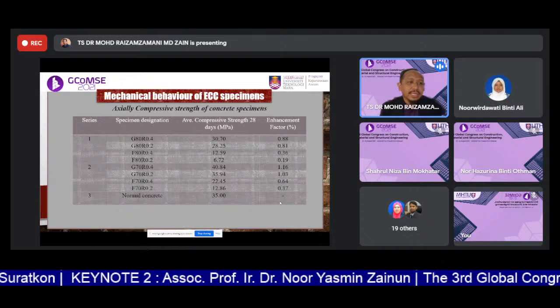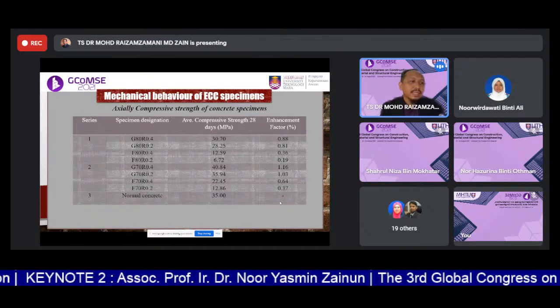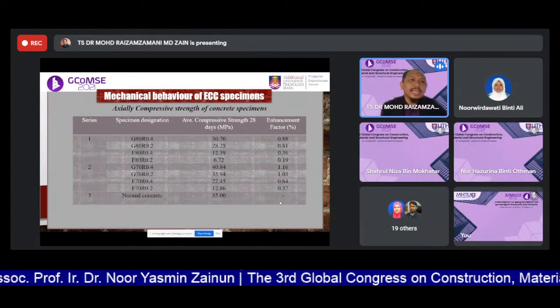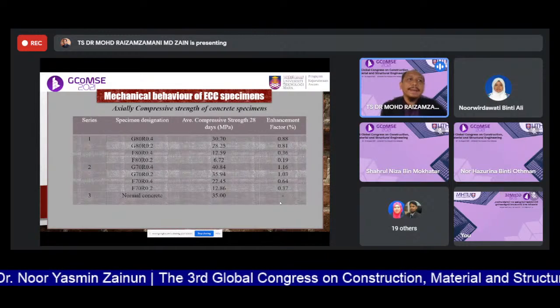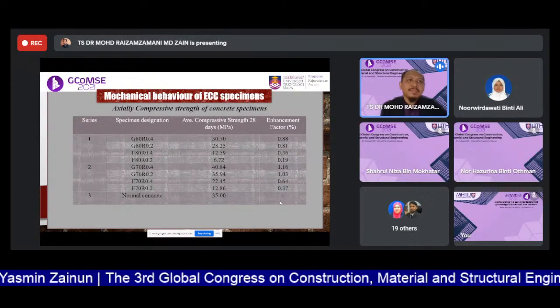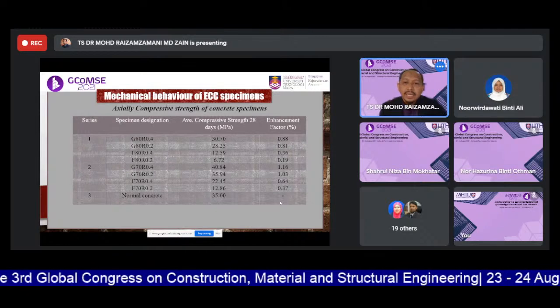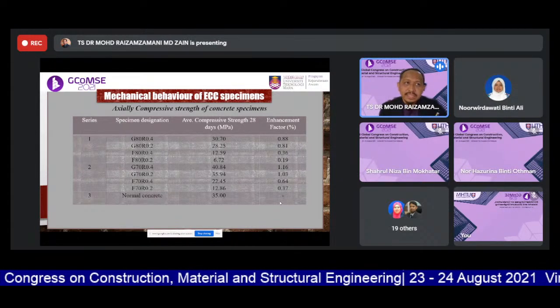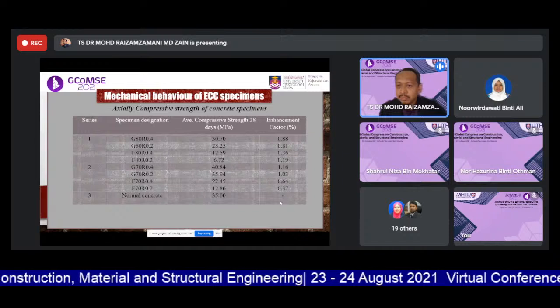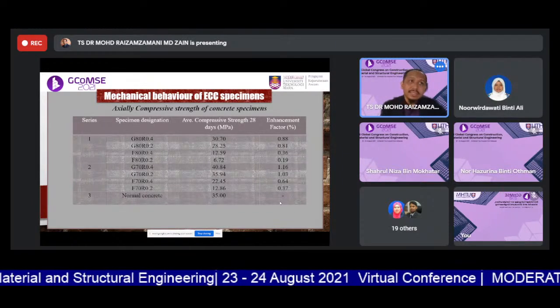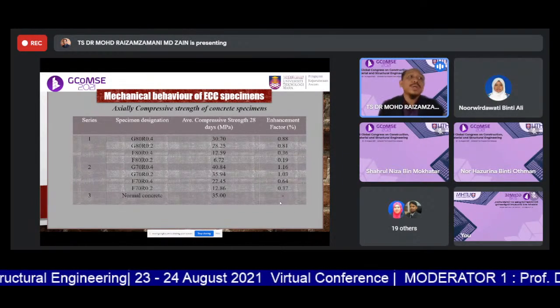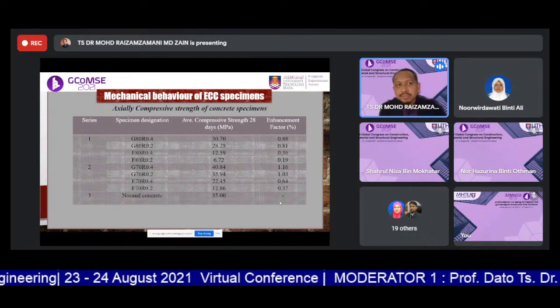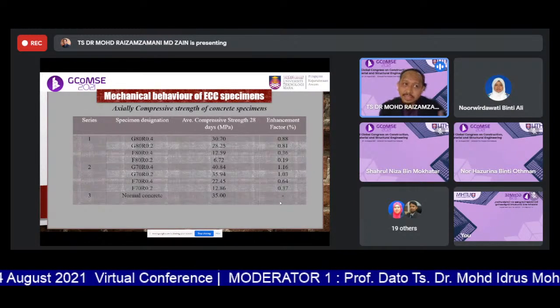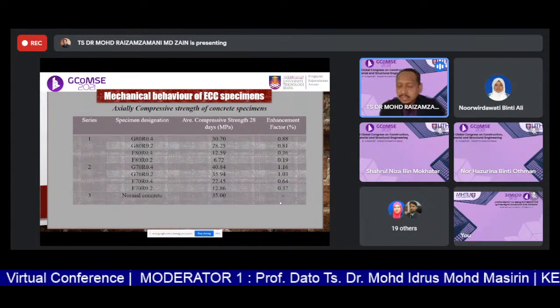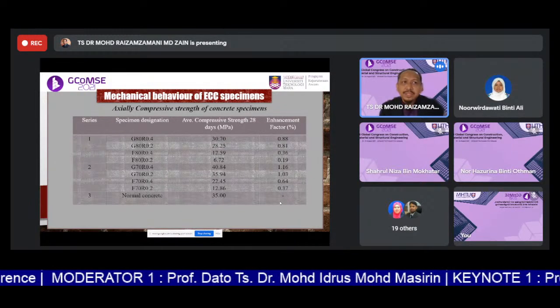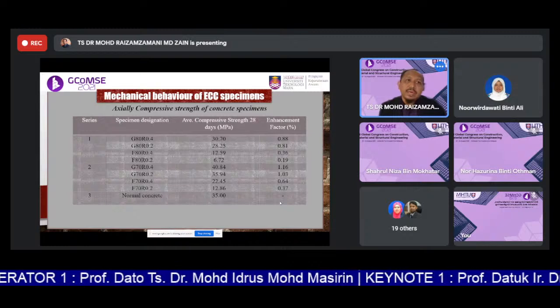Here, I can see that the use of 70% GGBS replacement of cement with PP fiber in the ECC specimen enhanced the compressive strength of the ECC specimen by 1.03 and 1.16 respectively when compared to the normal concrete. The increment could be attributed to the use of eco material like GGBS and the addition of fibers such as PP fibers, which have been shown to improve the microstructure of concrete.